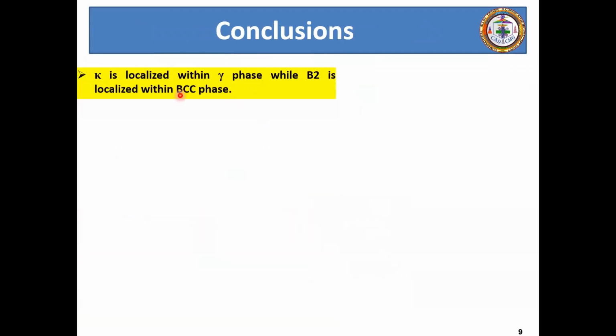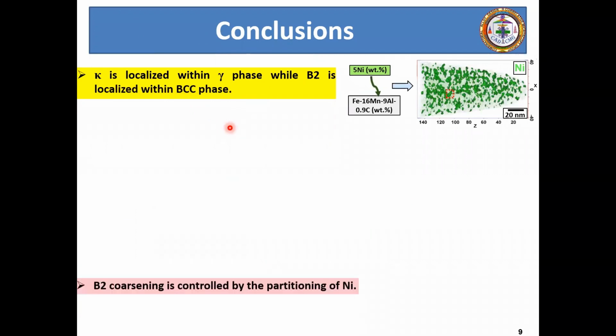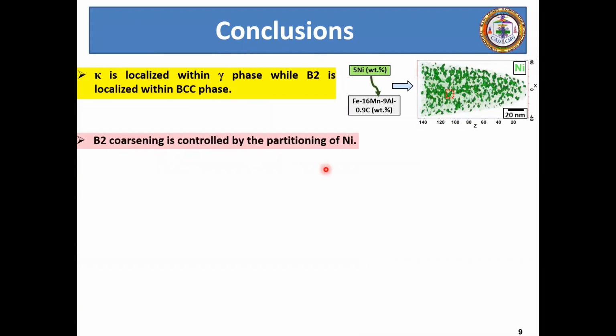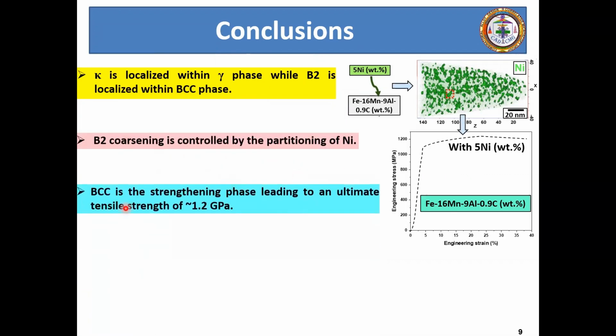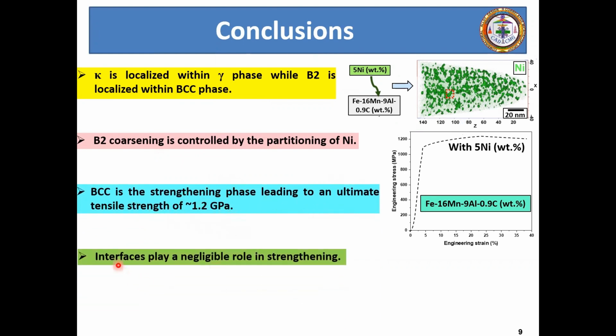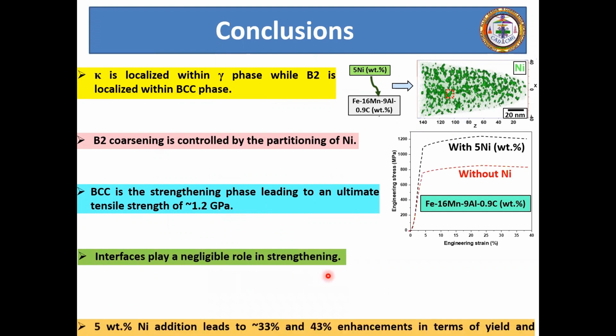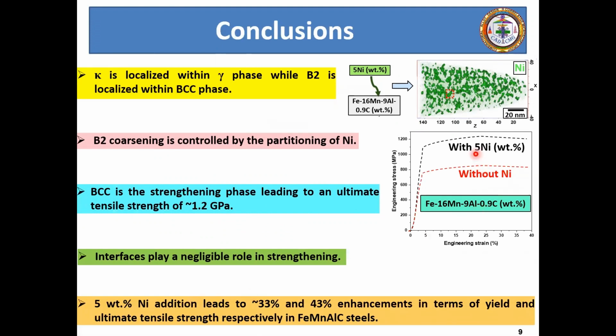So now with this, I would move towards the conclusions of my talk today. So the kappa is localized within the gamma phase, while B2 is localized within the BCC phase. Then the B2 coarsening is controlled by the partitioning of nickel. The BCC is the strengthening phase, leading to an ultimate tensile strength of nearly around 1.2 GPa. Then the interfaces play a very negligible role in strengthening. And finally, the addition of 5% nickel, as you can see from this particular plot, leads to nearly 33 and 43% enhancements in terms of the yield and ultimate tensile strength, respectively, in the FeMnAlC steels.